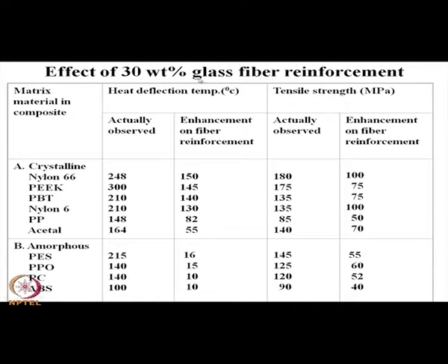This is quite expected, because glass fiber is a polar material having an oxide composition, and nylon 6, polyether ether ketone, polybutylene terephthalate, nylon 6,6 have such polar linkages. So, this polar-polar interaction makes very good adhesion of this matrix resin with the glass fiber. That is why there is enhancement of heat deflection temperature. Heat deflection temperature means the composite can stand without any dimensional instability up to these temperatures.